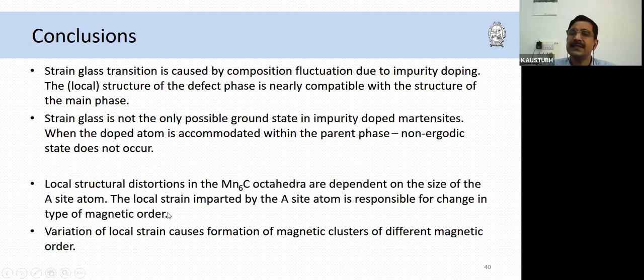The local structural distortion of these octahedra is dependent on the size of the A-site atom, and the local strain that is imparted by this A-site atom is responsible for the different types of magnetic orders that these materials exhibit. At the 50-50 compositions, it forms magnetic clusters with different magnetic order.